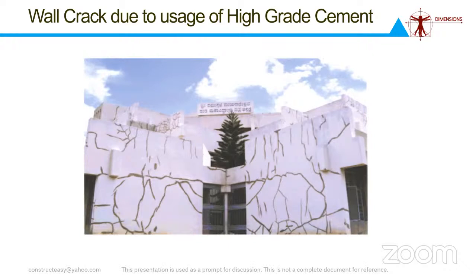OPC, of course, is a rapid. It's not technically rapid. It basically tends to set fast because of its fineness. The surface area is high, the fineness is high, therefore heat of hydration is high, therefore the shrinkage potential is also high because of the fineness, and this has happened. Had they used a blended cement or a low grade cement for the plastering, which doesn't require very high strength because it's only a rendering material. The plaster is only a rendering material. It's not a structural material. So if they had used a low grade cement, they could have avoided this.